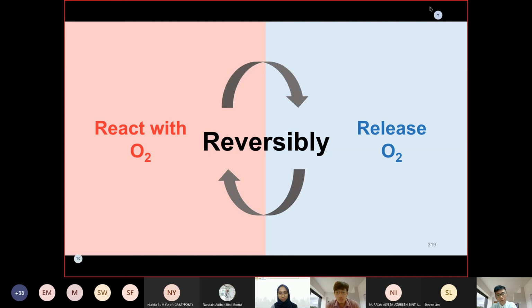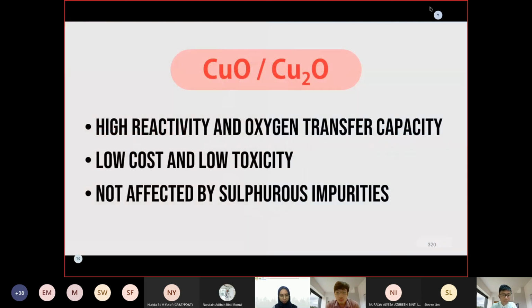Thus, the CLOU utilizes the fact that some metal oxides have a suitable equilibrium partial pressure of gas phase oxygen at a high temperature for combustion. Some metal oxides based on copper, manganese, and cobalt have this distinctive property and we'll discuss soon. The oxidized form of copper is copper 2 oxide and it will be reduced to copper 1 oxide.